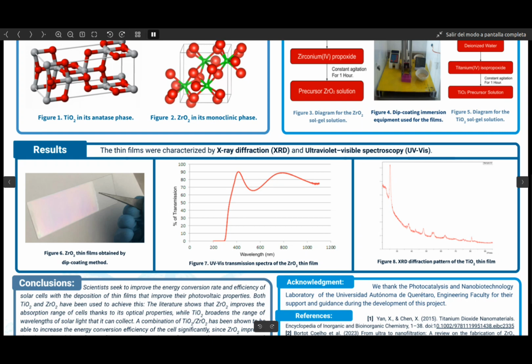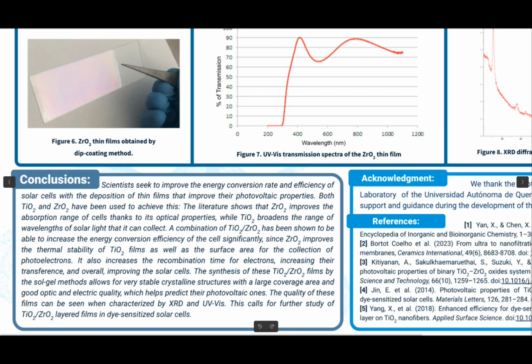These thin films were characterized by X-ray diffraction to determine the degree of crystallinity and the crystalline structure obtained from the diffraction patterns of the samples. Ultraviolet-visible spectroscopy was also carried out to obtain information about the electronic state of the films and their bandgap energy. The best combination of parameters will be used in following months of research to further test the photovoltaic properties of the synthesized nanomaterials. In conclusion, titanium dioxide and zirconium dioxide thin films are used to improve the energy conversion rate and overall efficiency of the dye-sensitized solar cells.